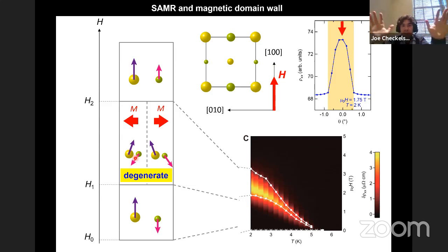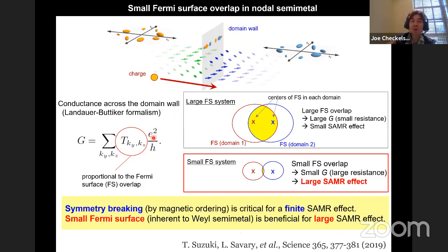And you only get these two states having the same energy when you're precisely having the field aligned along this direction. So it's kind of like a symmetry-allowed magnetic state. And in this state, you have a huge number of magnetic domains. So what's interesting is that that seems to couple in a very deep way to the topological aspects of the